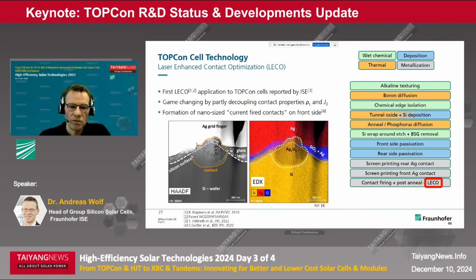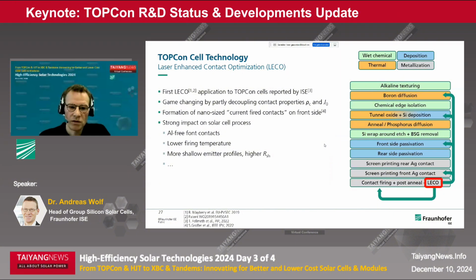And the major part of the interface under the silver finger is still passivated by the passivation layers, and this gives a very high quality of the contact regarding very low recombination parameters. This has been implemented, and it strongly affected the whole process chain.